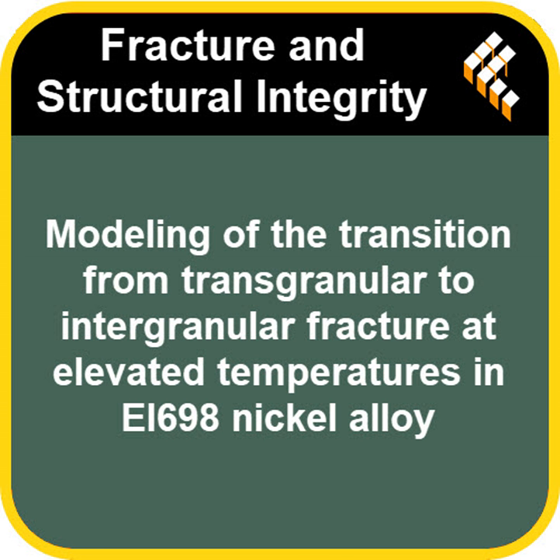Correct. And they then proposed a specific power law dependence for this grain boundary GC as well, again dependent on temperature, equation 14. The coefficients were carefully chosen so that the model predicted the switchover temperature from transgranular to intergranular fracture at around 400 degrees C, which aligns nicely with experimental observations shown in Figure 6. Okay, so they tuned the model to match that known transition point. Yes. And there's one more subtle but important detail, that characteristic length of the phase field model itself, the model's resolution. That was also made dependent on temperature, equation 15. This allows the width of the simulated crack zone to adapt realistically as the material properties change with heat.